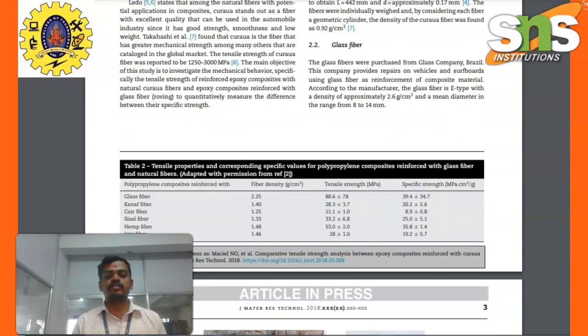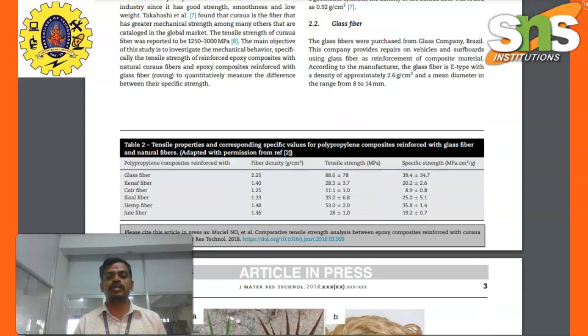Generally, the glass fibers were purchased from a glass company in Brazil. This company provides repairs on vehicles and surfboards using the glass fiber as reinforced composite material. According to the manufacturer, the glass fibers are E-type with a density of approximately 2.6 grams per cubic centimeter, and a diameter in the range of 8 to 14 micrometers.